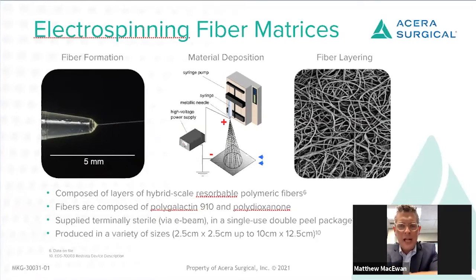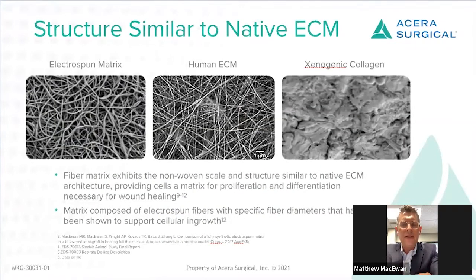And then as that bead of polymer is stretched and drops over a small gap, it stretches these fibers to the point where they're nanometers in diameter. So very small diameter fibers, smaller than individual human cells. And then we continually spray or deposit these fibers one layer on top of another until we get a three-dimensional matrix of these non-woven nanoscale or submicron scale fibers that you can see on the right. What's really exciting about these materials is that they mimic the same structure and architecture of native ECM. So even though they're synthetic in nature, they provide the same type of architecture as you have in the human tissue.